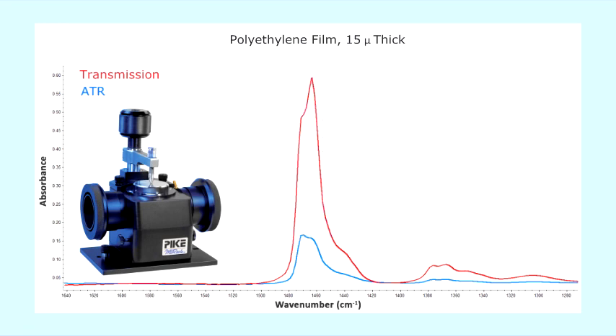Let's look at the CH2 bending absorbance band. Given the ratio of the film thickness to the effective penetration is roughly 4, we would expect the absorbance band to be roughly 4 times greater for the spectrum obtained by transmission, which is exactly what was found.